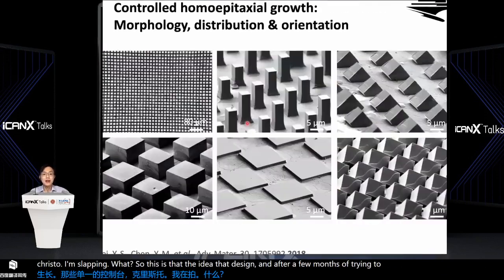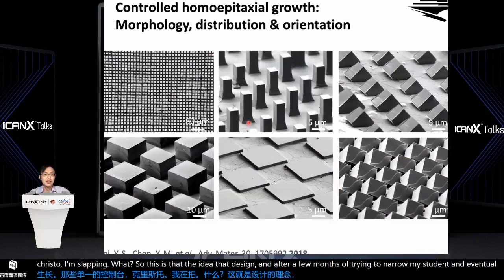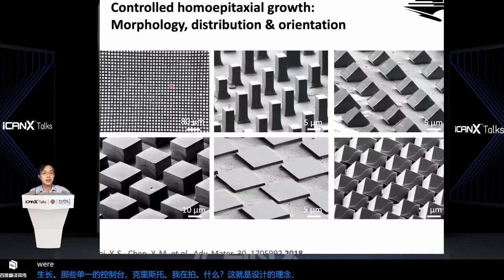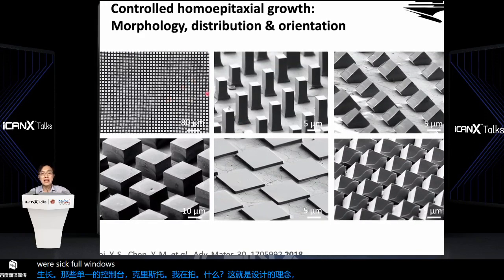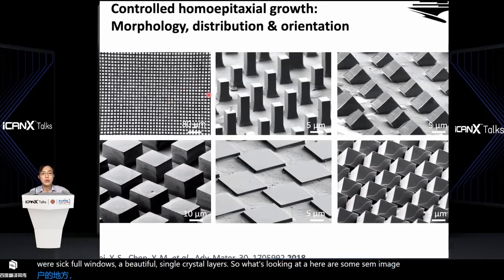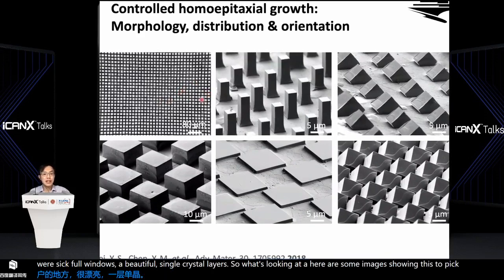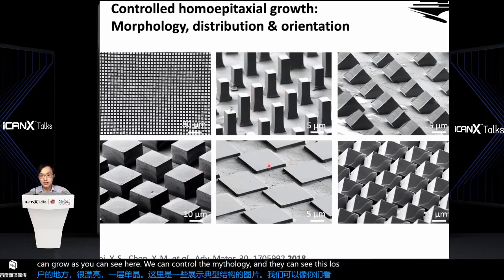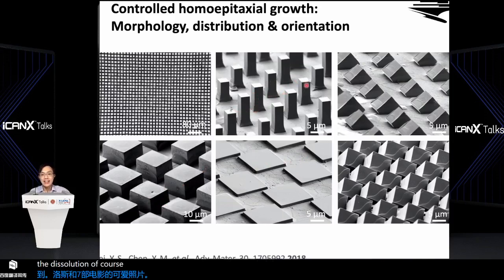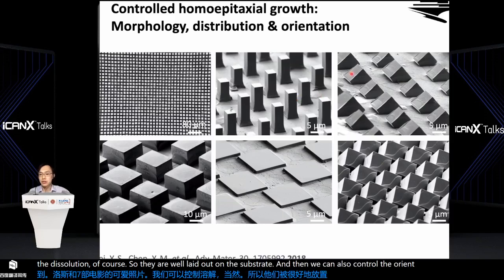And after a few months of trial and error, my students were eventually successful in growing those beautiful single crystal layers. So what you're looking at here are some SEM images showing the typical structures we can grow. As you can see, we can control the morphology, and you can see rods, cubics, and thin films. We can control the distribution, of course, so they are very well laid out on the substrate. And we can also control the orientation of the microstructure by using different orientations of the substrate, right?